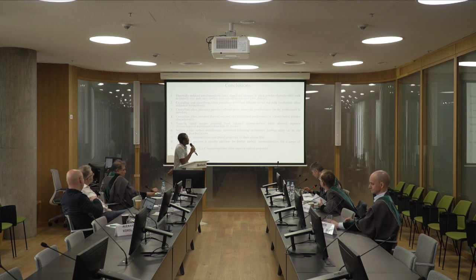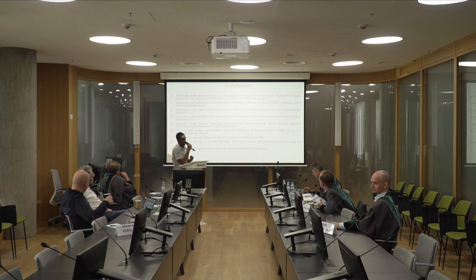Okay, thank you very much. So after thermally induced phase transformations, we see huge color changes for the roasted and for the calcined powders. We also see, because we crystallize the powders, we obtain main phase cristobalite, and we see that for the calcined powders, we have a smaller cristobalite crystallite size and much bigger cristobalite crystallite size for the roasted powders. We see a drop in the surface area for the heat-treated powders, and also for the pore size, we see an increase because during thermally induced phase transformations or just thermal treatment of diatomite, impurities that block pores are decomposed. And lastly, the particle size increases slightly.